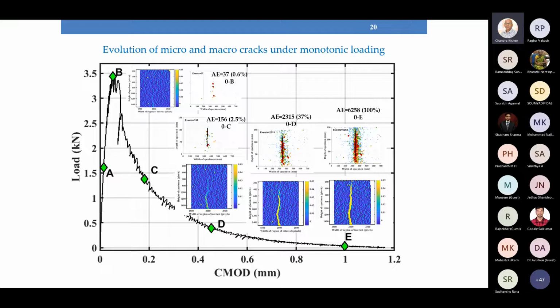So if a micro crack appears inside the specimen, these are all the micro cracks which are appearing inside the specimen, which are projected on the surface. On the surface, we have projected all the micro cracks which occurred, and the smaller dots, the light blue ones, are the events or the micro cracks with low energy. We have classified them into 4 energies. The smallest is the blue one, and the red one corresponds to the high energy event.